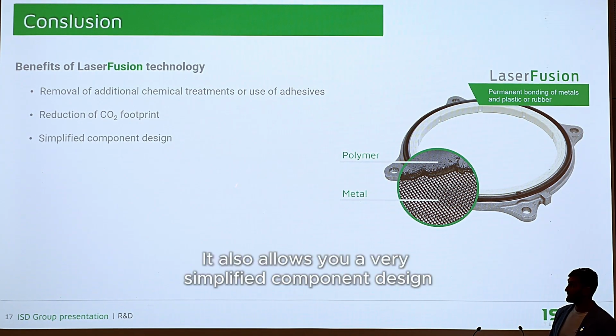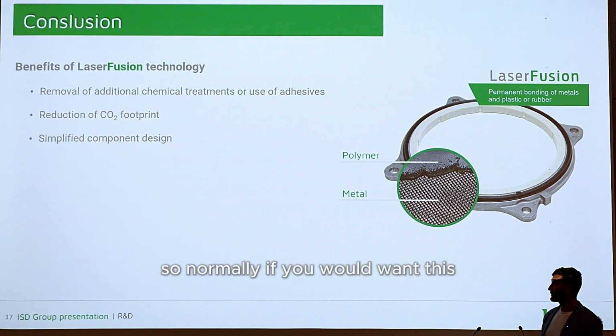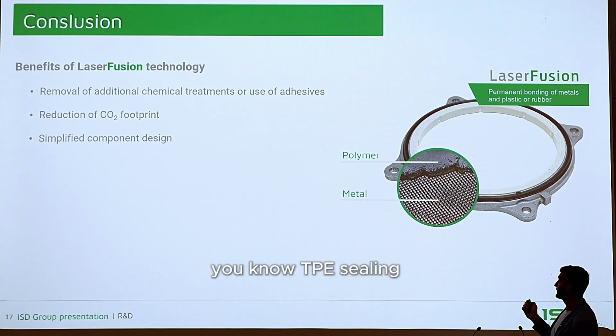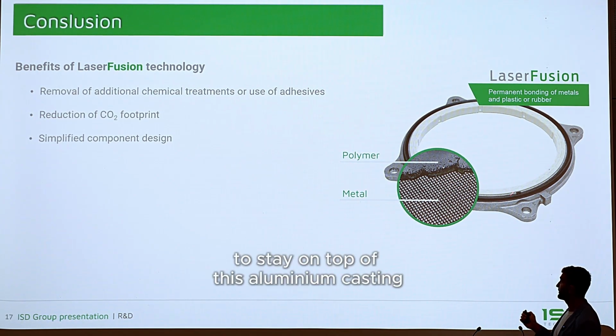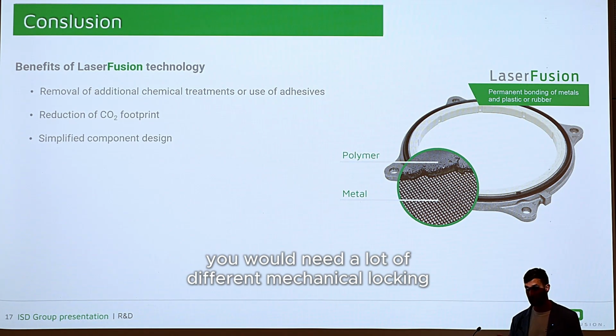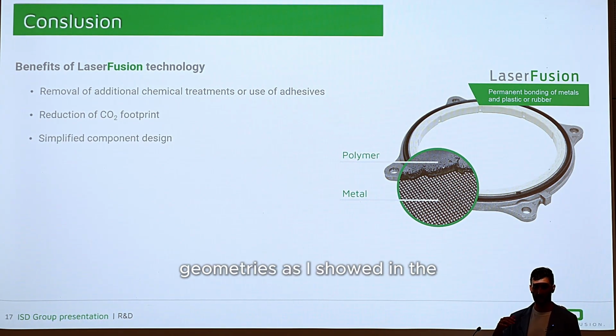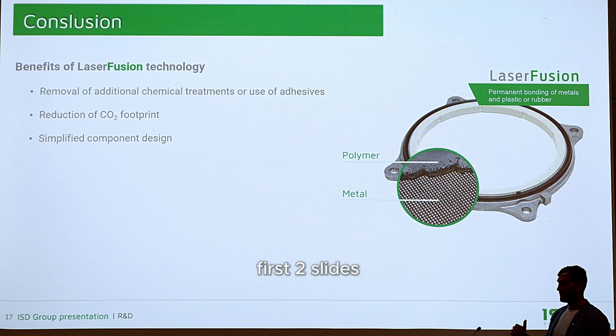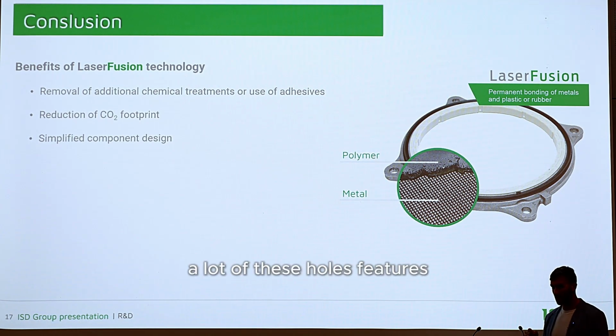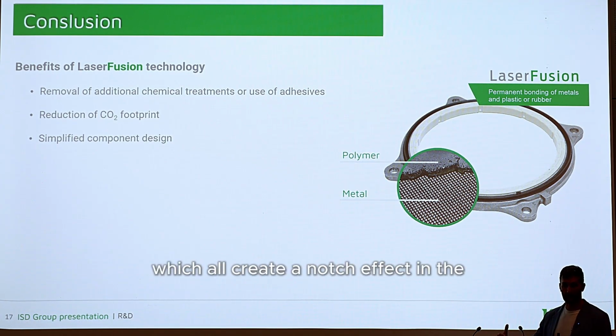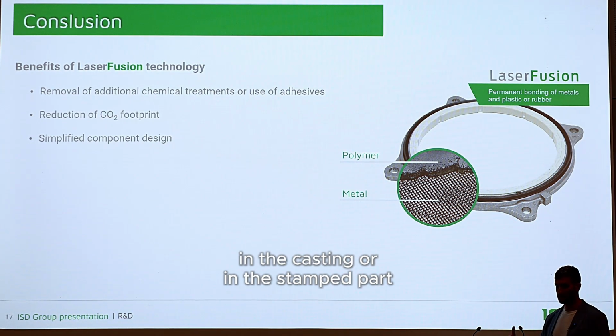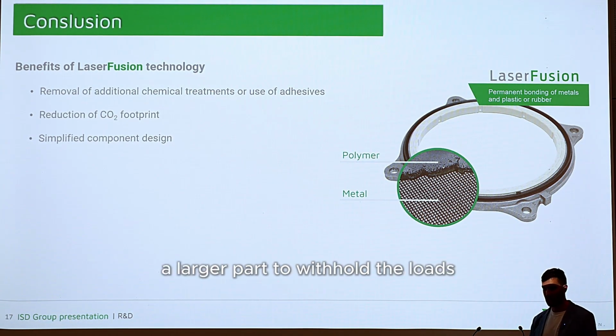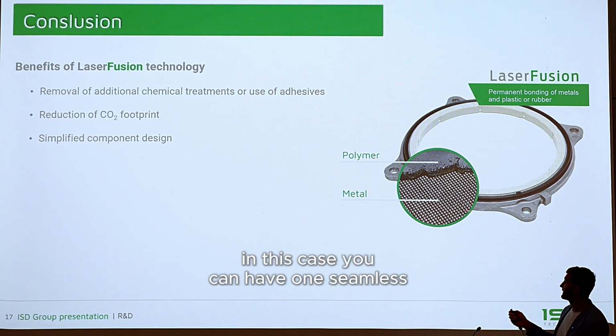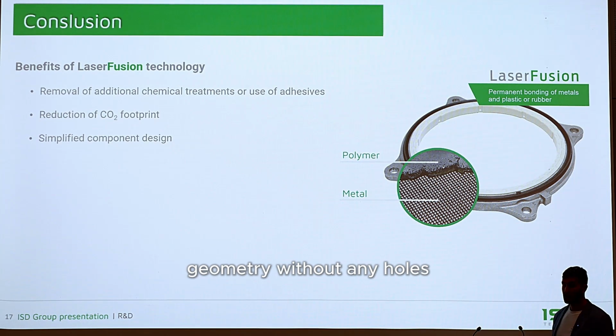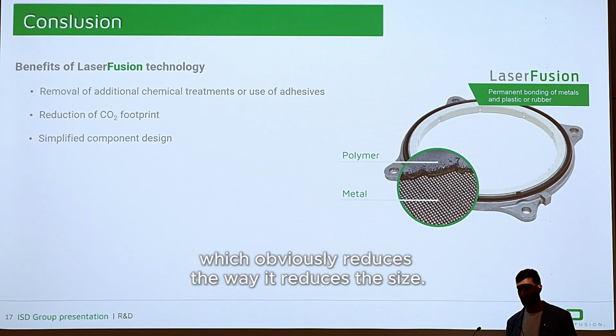It also allows you a very simplified component design. So normally, if you would want this TPE sealing to stay on top of this aluminum casting, you would need a lot of different mechanical locking geometries, as I showed in the first two slides. A lot of these hole features, which all create a notch effect in the casting or in the stamped part, and that's why you need then a larger part to withstand the loads. In this case, you can have one seamless geometry without any holes, which obviously reduces the weight, reduces the size.